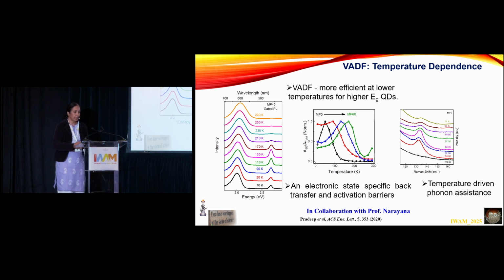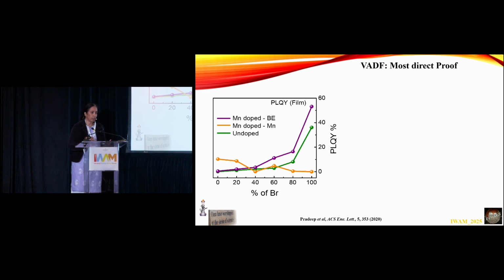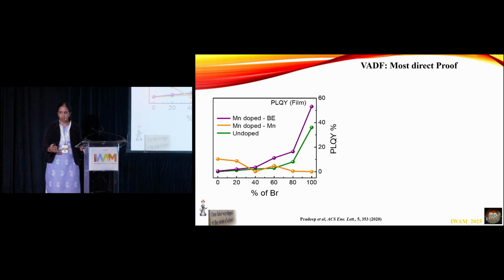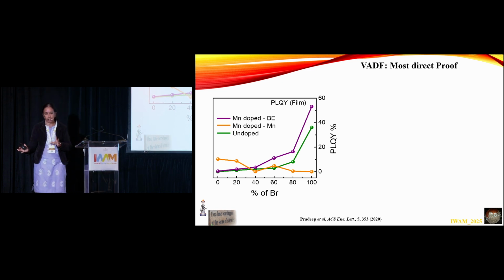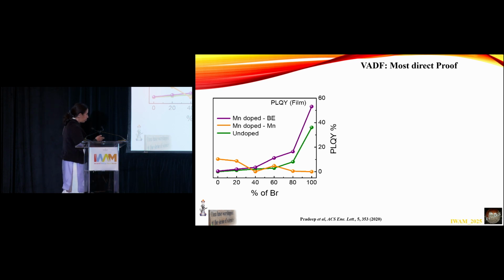So basically now we have shown that manganese can interact, have a vibrational coupling, and what is the direct proof? Now if this is indeed coupling, I said that emission channels should become more radiative. I should not be losing energy as heat, which means the quantum yield should increase. So we did see that with increasing manganese doping, the manganese emission of course is going down, but the band edge emission is increasing the radiative pathway from 40% to 60%.